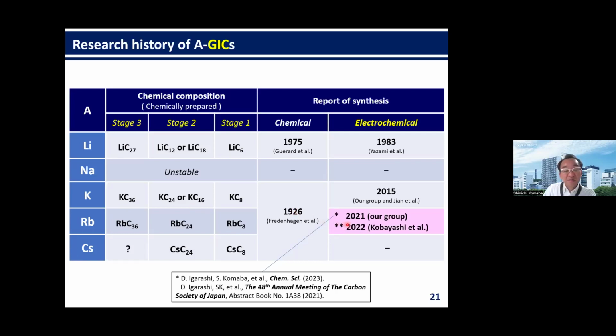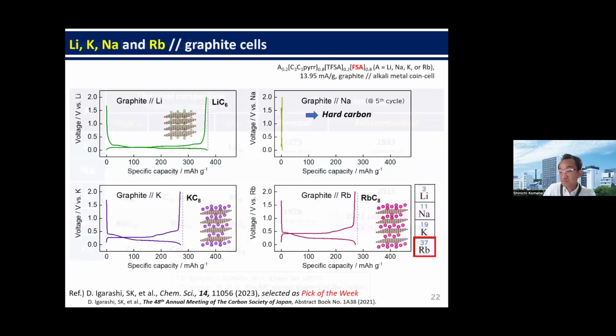And we recently achieved the reversible electrochemical intercalation of rubidium into graphite. The data is here. In the case of lithium, as you can see here, the reversible capacity is approaching 400, corresponding to the LiC6 stage 1 compound. In the case of potassium and rubidium, the stage 1 compound corresponds to KC8 or RbC8, and the reversible capacity is about 280 milliampere hours per gram. In the case of sodium, as I already mentioned, the electrochemical reactivity is negligible for graphite electrode in carbonate sodium cells. So the best choice is hard carbon for practical sodium-ion batteries.